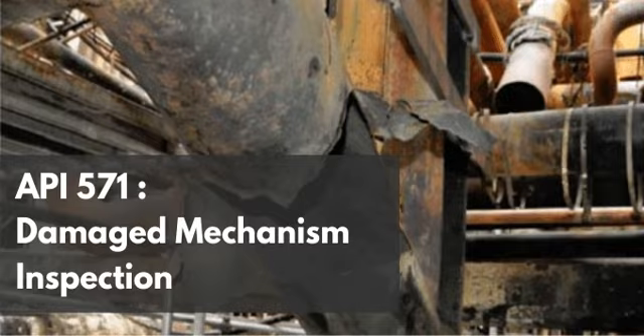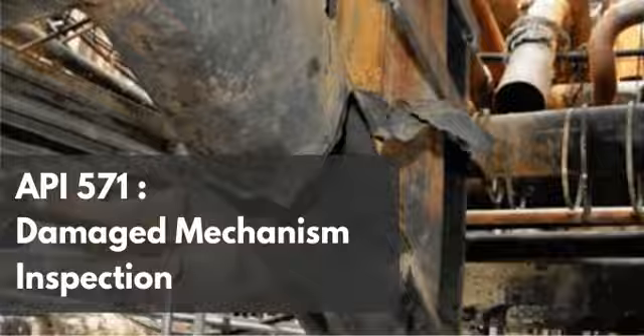Okay, you just mentioned it being highly magnetic, and this is where my mind was totally blown by the source material. Great field trick. The data details qualitative field tests for carburization. It states that a change, specifically an increase in the level of ferromagnetism, can occur in some alloys. This means a magnet might suddenly stick to a normally non-magnetic tube.